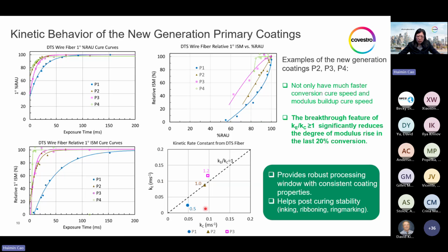And most strikingly, it is now moved over to the top half of the chart, meaning breaking the barrier of this line of KE over KC being 1. And I did not even show the P4 because the P4 is way on the top, having a very high ratio. The benefit with this feature of KE over KC equal to or higher than 1 are very significant.